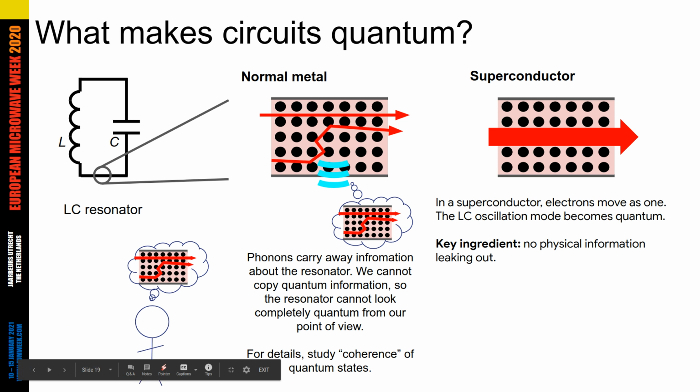To get our resonators superconducting, we put them inside dilution refrigerators. A dilution refrigerator uses helium as its working fluid and can get down to 20 millikelvin, which is colder than deep space. Superconductivity in aluminum, the metal that we use in our circuits, only requires cooling to about 1 Kelvin, but it's easier to keep the quantum states alive if we cool them down further to 20 millikelvin. Basically, the issue is that lower temperature suppresses some of the processes that steal the circuit's quantum information.